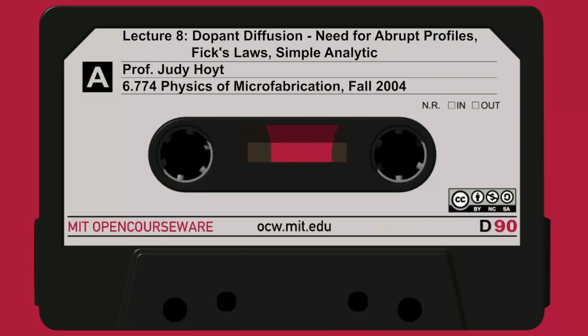Well, as we'll see when we talk about it in Chapter 8, it's done at room temperature, essentially, so you can mask it with simple materials like photoresist. It gives you, probably most importantly, a very precise control of the number of atoms that are introduced per square centimeter into the substrate. It also gives you very accurate depth control. So those are key advantages.